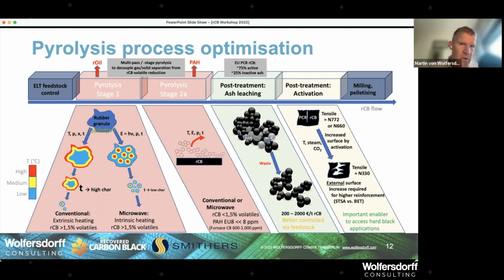And then we have a lack of recovered carbon black in that particular rubber compound. And then after that, we might wonder why the rubber properties are not as we want them to be, because half of the recovered carbon black went out in the degassing stage. So that is why we need to granulate.